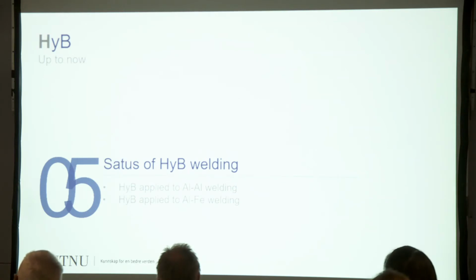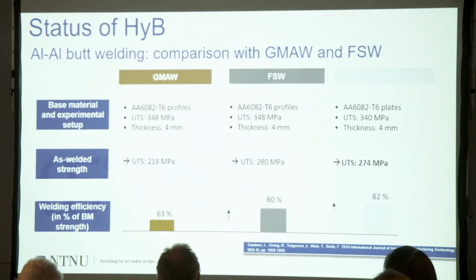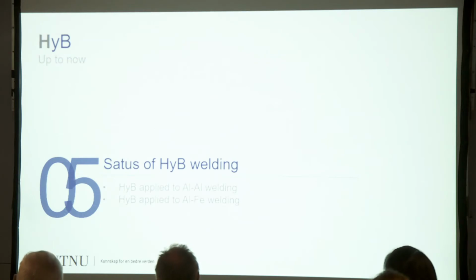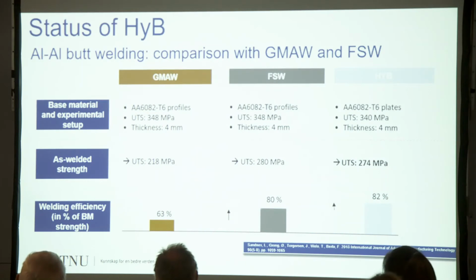We study the status of HyB, and in particular I will be focusing on aluminum welding and aluminum steel welding. Dealing with the status of HyB for aluminum welding and comparing this technique with gas metal arc welding and friction stir welding, we have seen that under static loading we have almost the same ultimate strength of the bonding of the friction stir welding. And the welding efficiency is almost similar.